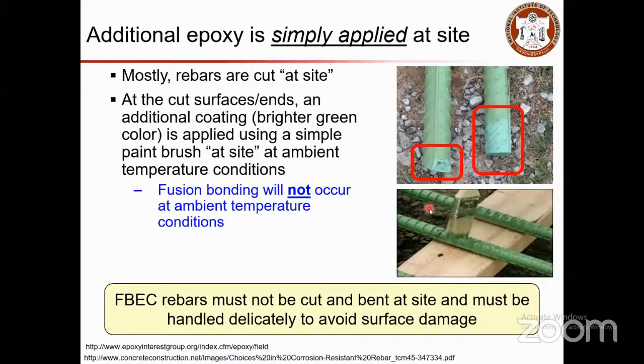So mostly rebars are cut at site. When you do cut at the sides, there is a possibility that if the coating thickness is more, it may get peeled off. If it is peeled off, people may not think further, they just tend to fix it then and there and they recoat it. And the recoating is going to affect the performance mostly.